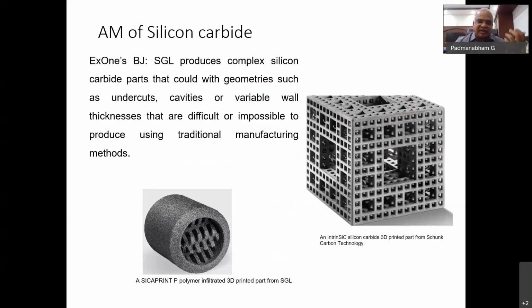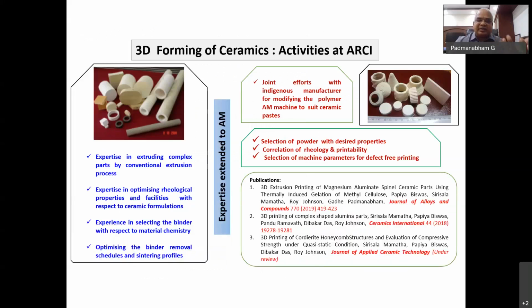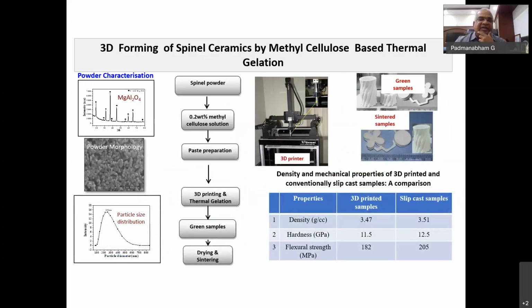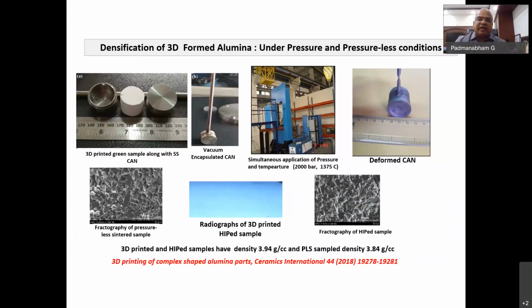Similarly, silicon carbide is a very highly technologically important material. Very fine features can be built using the binder jetting method for ceramics. And at ARCI, we use the extrusion method to make different ceramic shapes, which you are seeing here. One of our innovations has been 3D forming of spinel ceramics by thermal gelation techniques. You make the paste using methyl cellulose, then 3D print, then thermal gelation, and get the green samples, and then sintering. Then you get the density you're looking for, and you can see properties comparable to slip casting samples. And also, we can do pressureless sintering.